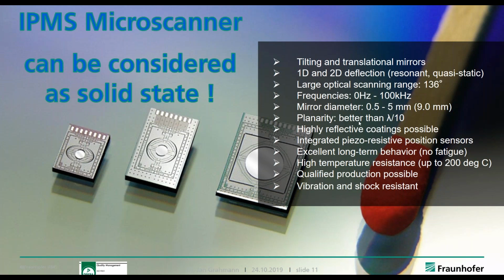Additionally, the planarity is an important thing I did not elaborate on today, but we always looked at the deformation of the mirror plates in movement is low enough so that there's no influence on the actual reflected laser spots mostly. We can provide high reflective coatings. We do have a position sensor integrated on chip. We have an excellent long-term behavior due to the technology used. So the single crystal silicon, there's no fatigue, which means on the other hand that we can also withstand high temperature, up to 200 degrees Celsius.